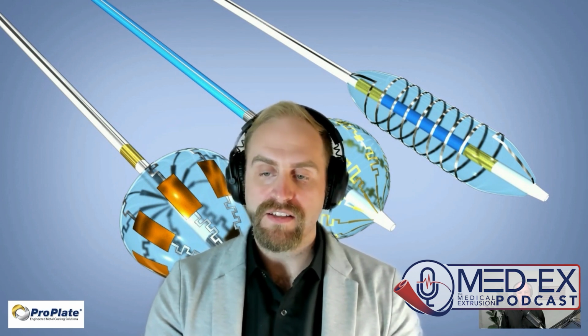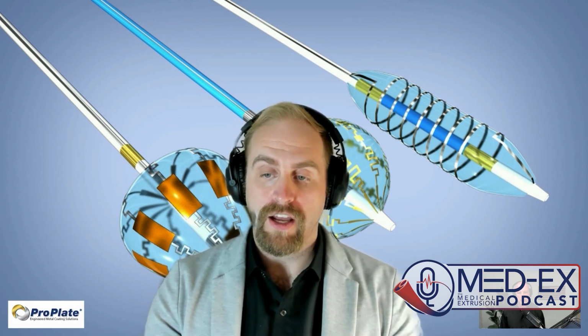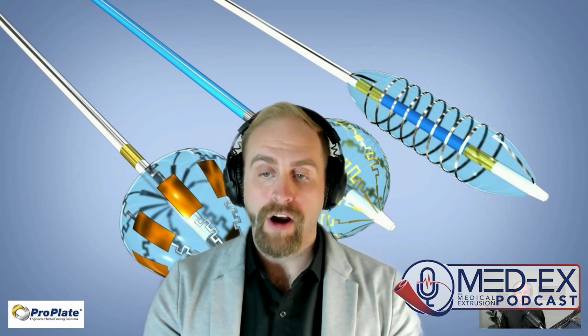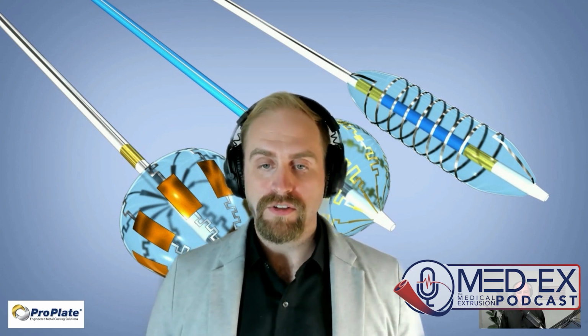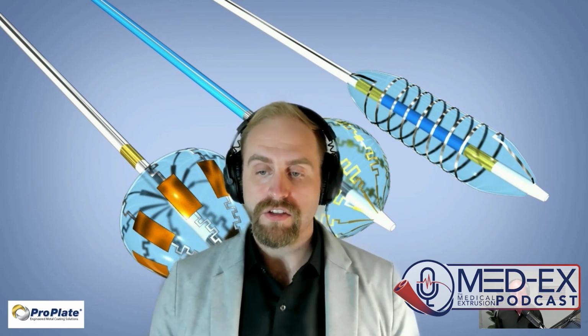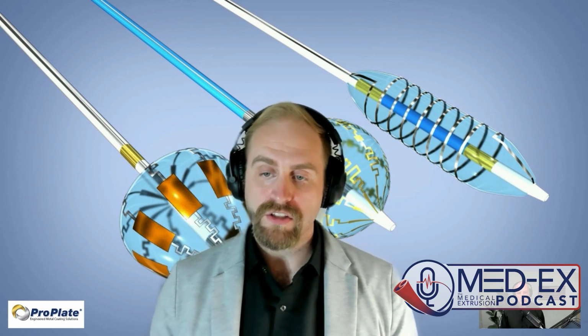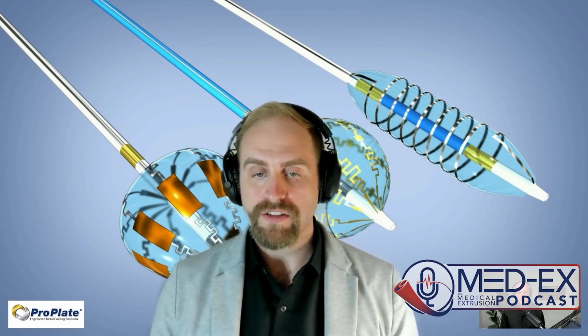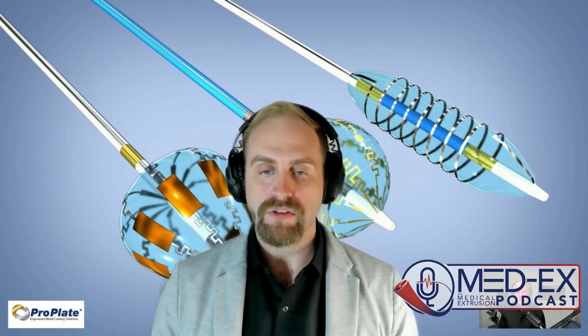But then also the process itself creates grain structures that are more stretchable. And then we're even applying to the balloon in an expanded state so that, when that goes back to that state, when it's being used, you're not going to have delamination or cracking of those metal layers. But each application is different. So the thicknesses can definitely range depending on if it's being used for ablation or stimulation or sensing, like I mentioned, for those potential uses.